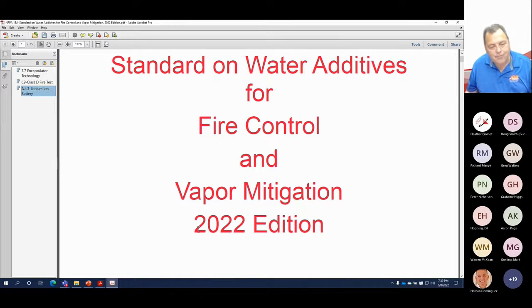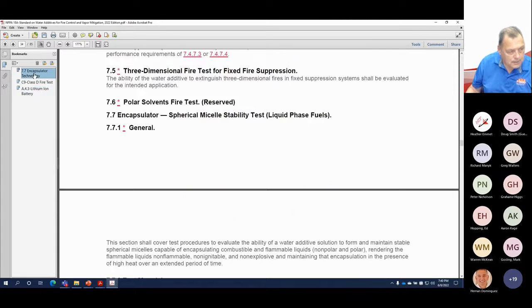This is a significant technology. This is a significant advancement in the fire protection industry. So I would say this is as significant as AFFF was back in the 60s. It's fluorine-free, biodegradable. Here, it talks about encapsulator technology, a spherical micelle stability test. So when you run, say, a UL 162 test, a lot of people think, well, that's a fire test. But if you take a step back and look at it 180 degrees, it's really a bubble or film integrity test. If I have really crappy bubbles, I'm not going to put the fire out.